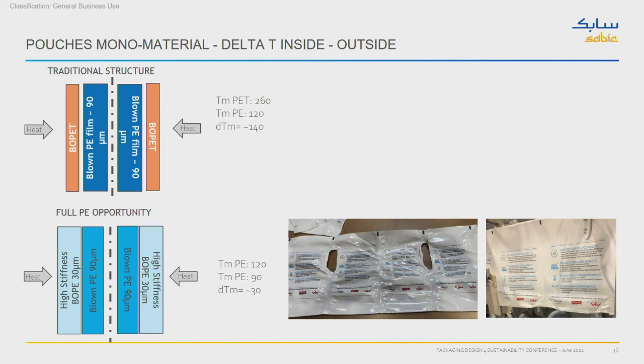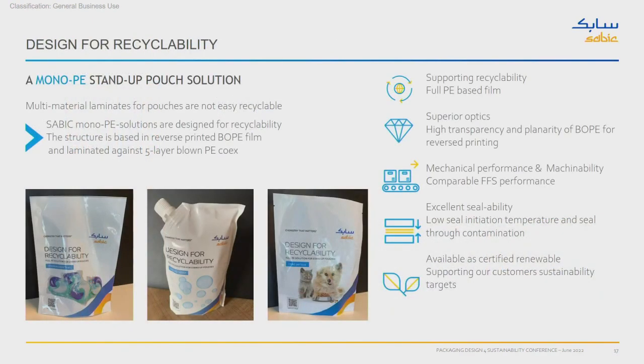And that is what we've done. You see some examples here. Designed for recyclability. Why? It's a monomaterial solution. We call it at least a monomaterial solution. Yes, there is an adhesive in there, true, but it consists of the oriented film, oriented BOPE on the outside, and a blown PE on the inside. And by that, we have a full polyethylene solution. That one is suited for mechanical recycling, and is also suited for advanced chemical recycling. Why? It's only polyolefins. So we can recycle them more easily in mechanical as well as in advanced feedstock recycling ways.